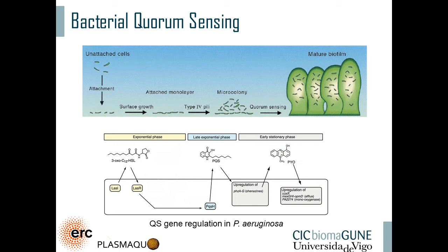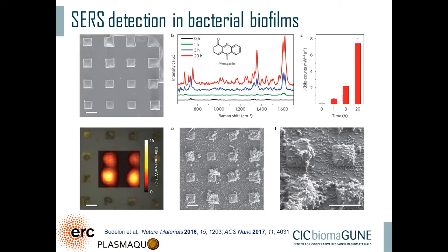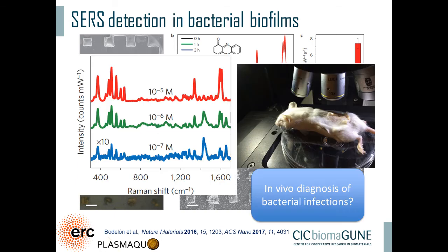And so it's important to have a method that allows you to read that communication in a non-destructive manner. And so what we did in the end was to have these pillars of oriented nanorods covered with silicon oxide and infiltrated with a mesoporous film. And then we actually grew bacteria on top, and we started to see the signal of this molecule, pyocyanin, at very early stages during the growth of the bacteria, so we could actually see when they start to create these biofilms at some point. In fact, we also did a similar piece of work with hydrogels that could be implanted below the skin of a mouse. In this case, this is a dead mouse.